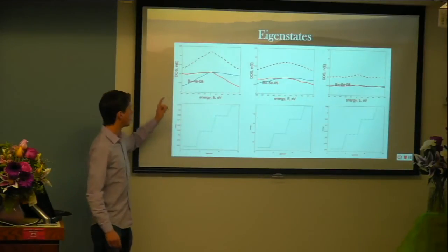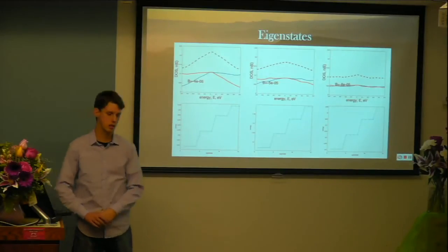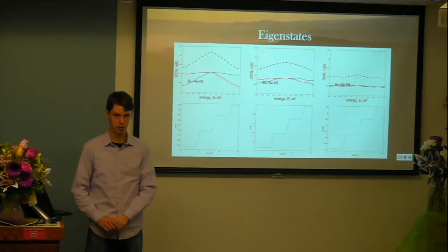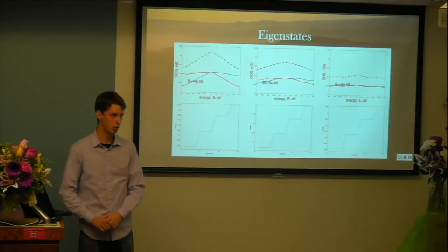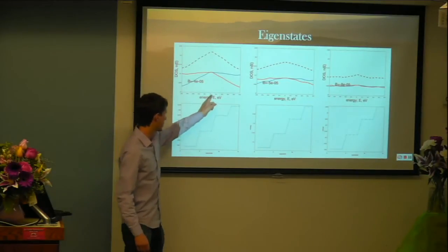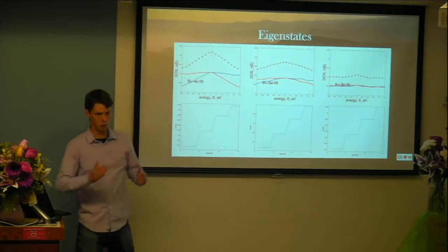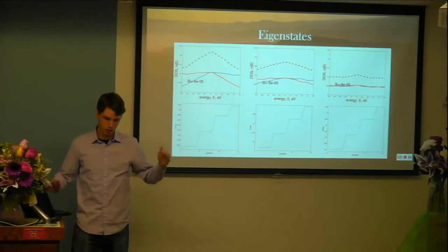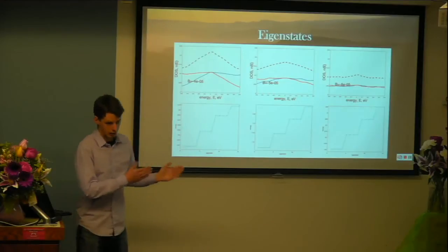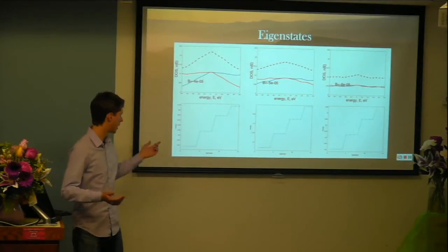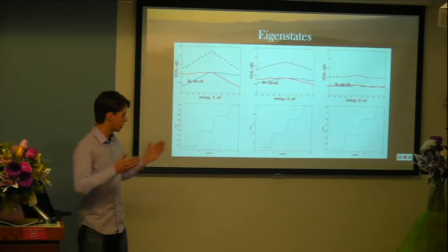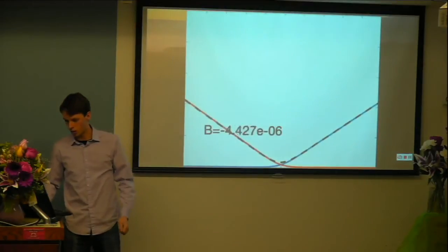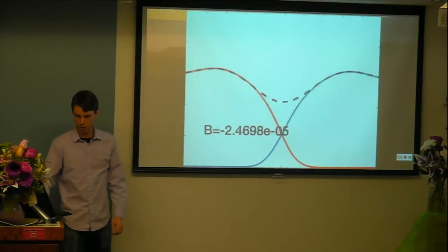What was determined from seeing this peak in the density of states is that it is evidence for a superconductor. I believe you can look at Fermi's golden rule for showing that when the density of states increases at a specific energy so sharply, it could indicate that a superconductor is being formed. And again, it flattens out afterwards, but that is something that is known to happen for density of states as the magnetic field is increased. So that doesn't prove this is true, but it gives further evidence that this is reliable. And this is just a video of all of those mapped out, what that would look like.